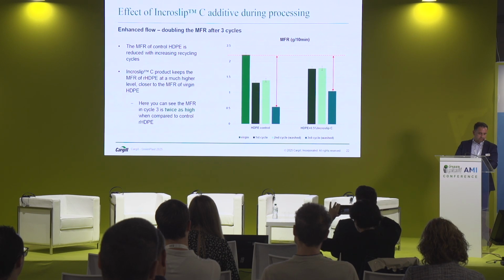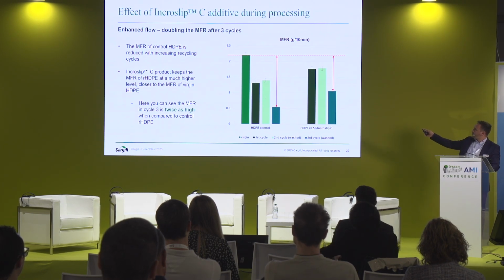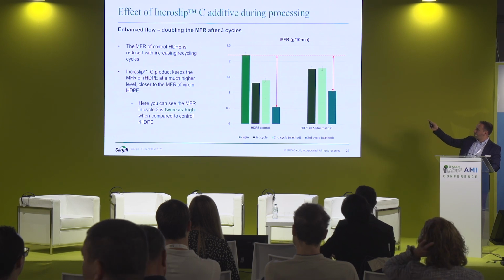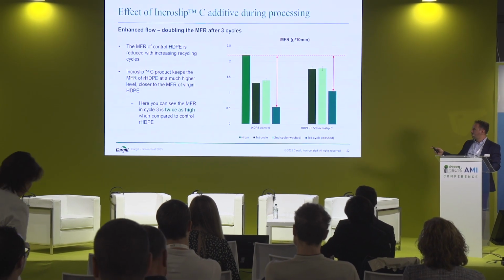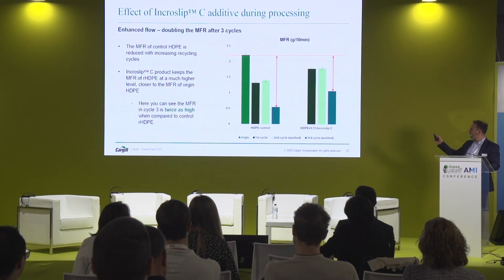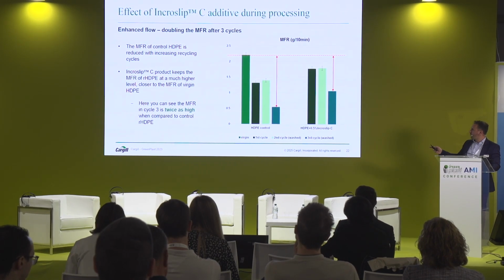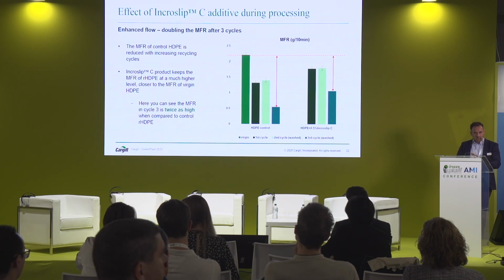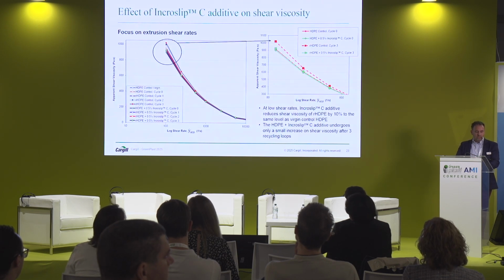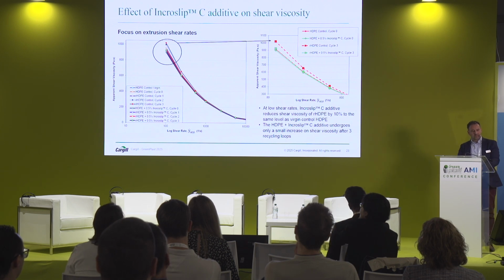This is exactly what I'm talking about. You can see the blue column, which is reduced down to 0.5 from around 2.2. That's on the blank recycled HDPE. With the additive, it's just over 1, so it's 2 times better. That was enough for us to start getting more and more curious and trying to understand what is happening, why this is taking place, and what is the mechanism. So we moved on to capillary rheology to investigate it a bit further and more in depth.